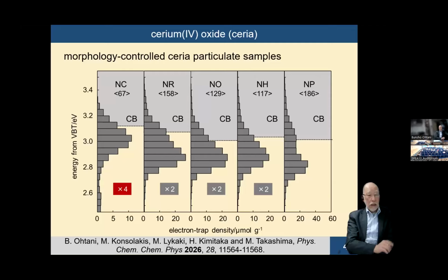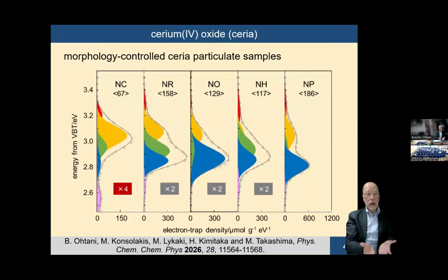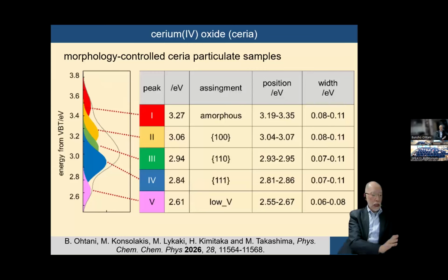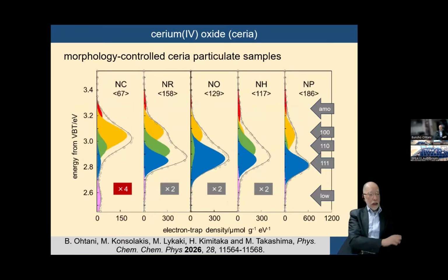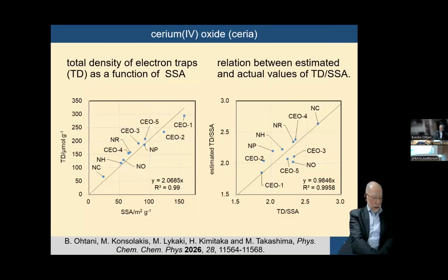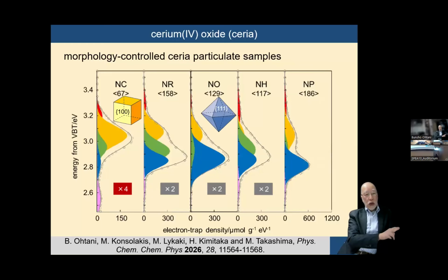We checked this by using ERDT-CBV and obtained those patterns, which are deconvoluted into 5 peaks. And I have no time to explain why we assign them, but of the 5 peaks, the higher energy one is amorphous, and then 100 facet, 110 facet, 111 facet, and low valency, for example, Ce2O3 surface. So for those samples, the main peak is different depending on the morphology. And then the cubic sample, so many papers reported this as a cube, only showing the 100 facet.